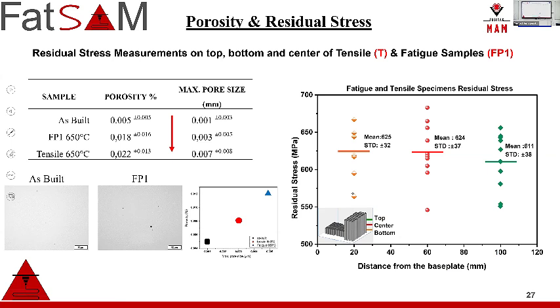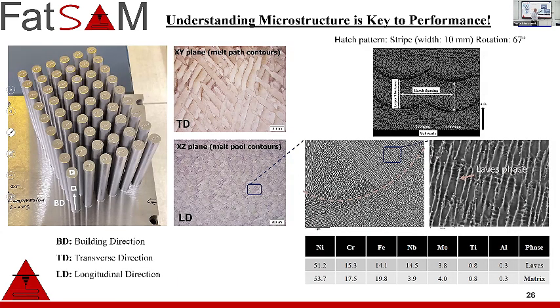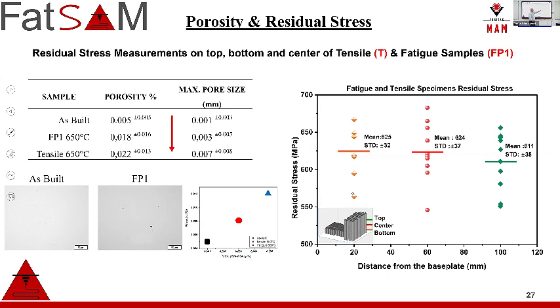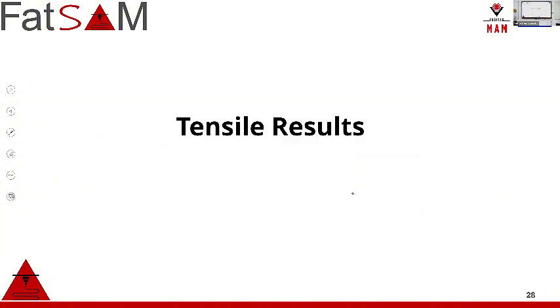But another comment, when we machine this sample, we are still working on it, but our initial insights are that due to this equiaxed columnar structure change, as well as machining effect, which releases a little bit of residual stresses, the tensile residual stresses go from 624 down, to compressive, minus around 300 megapascal compressive stresses. But we are still working on it and we need to confirm it, but we will see the results in this project. This is one of the most important parameters we would like to provide